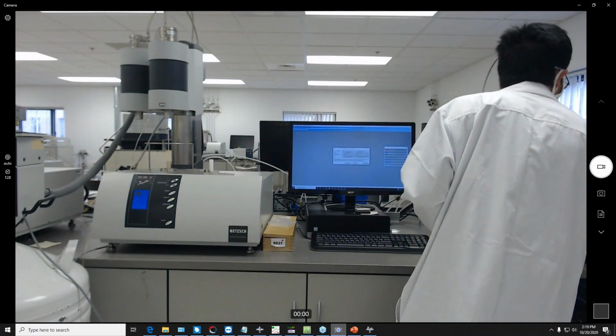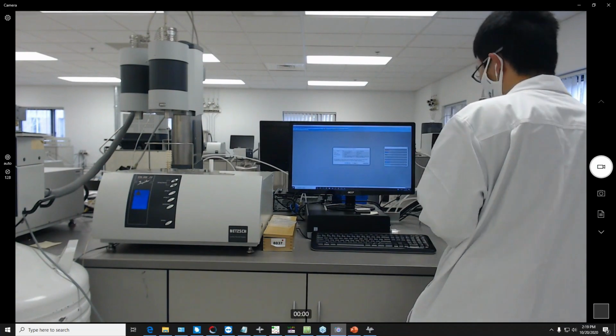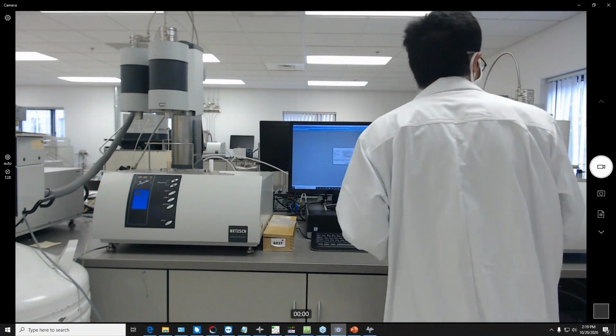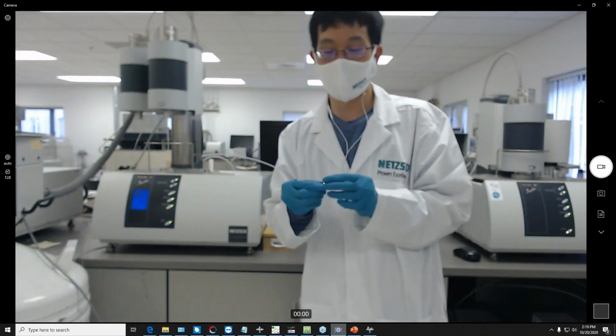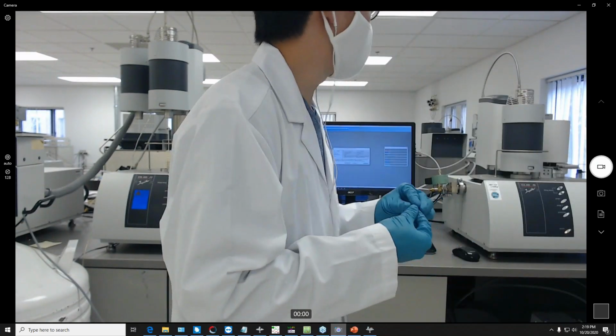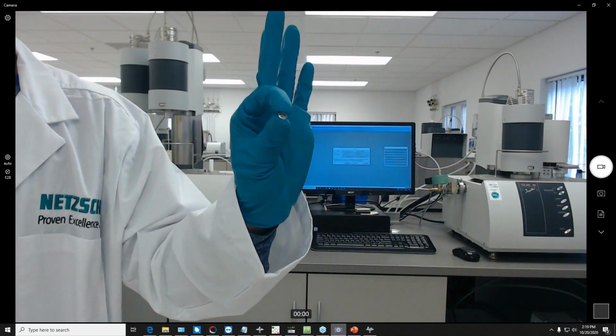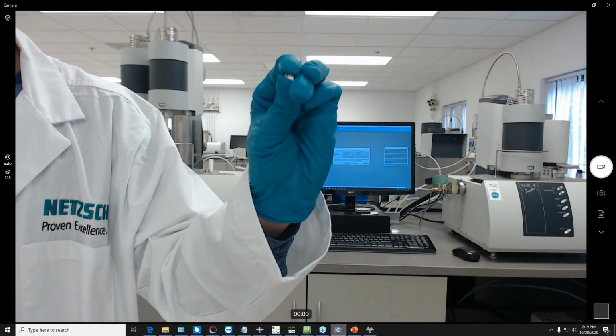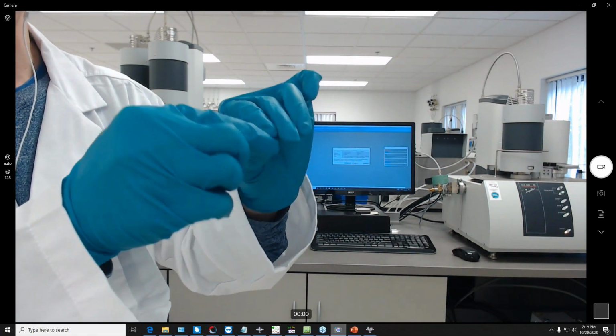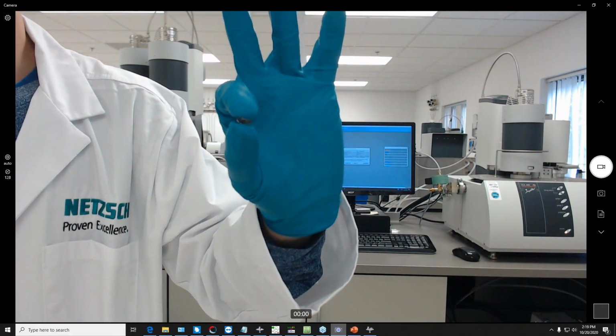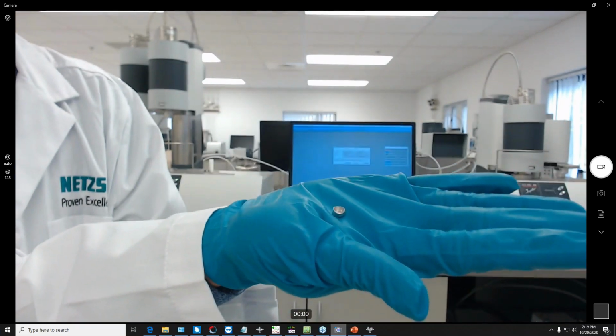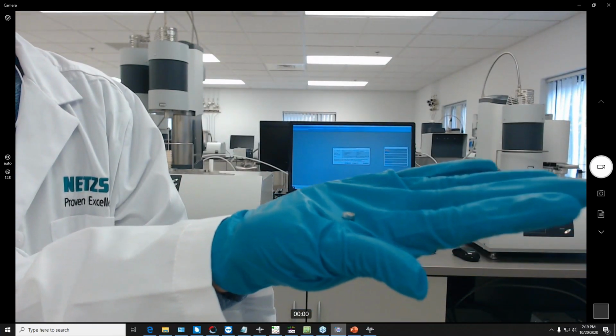Now, after cleaning the crucibles, especially platinum, you might accidentally deform or warp them. Here I have a platinum crucible, and I'm just going to demonstrate by squeezing it. If you accidentally squeeze it too much, or if you drop it and dent it, so now my crucible is, let's see if I can get a better image of it, not exactly round anymore.